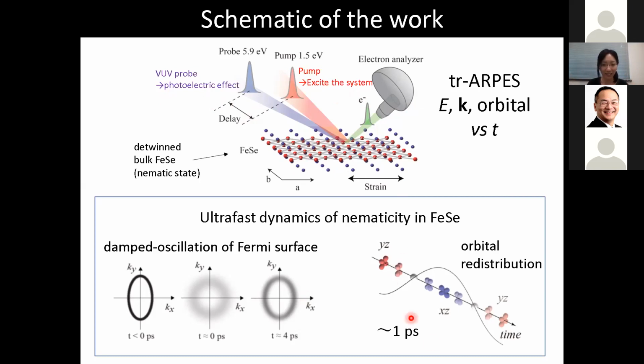And this is a kind of result I already showed here. But with this measurement, we observed a very ultrafast change of the Fermi surface shape and also an oscillation of the Fermi surface. Today I didn't bring this part, but we also successfully observed the orbital components changing from YZ to XZ and then YZ. All this kind of oscillation occurs on a time scale of 1 picosecond. So from the next slide, I would like to show you the results.